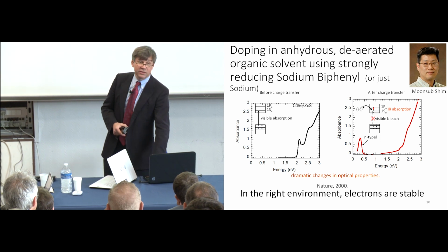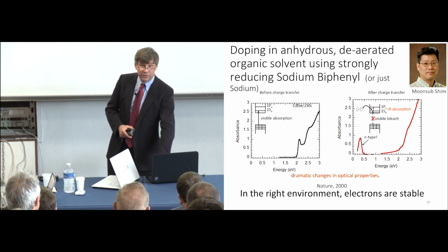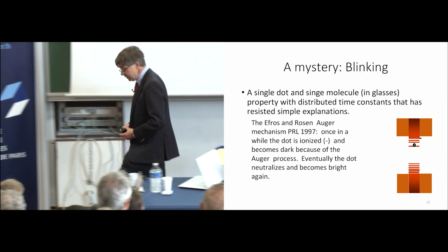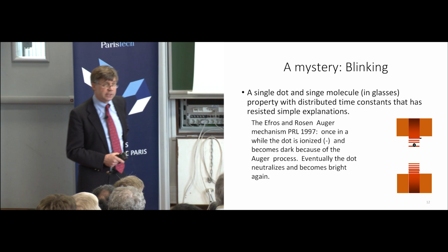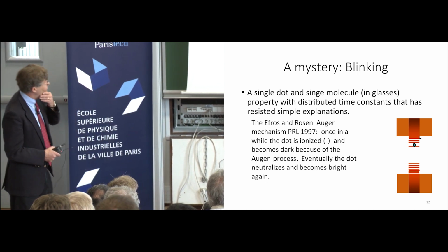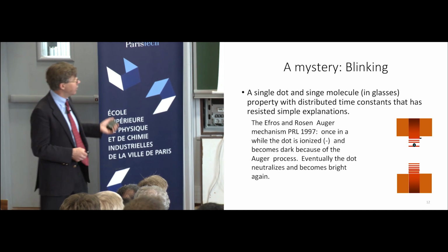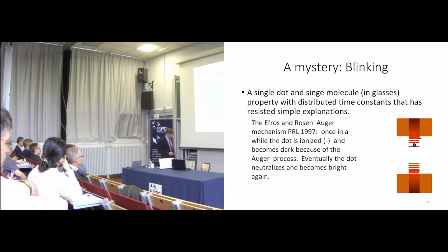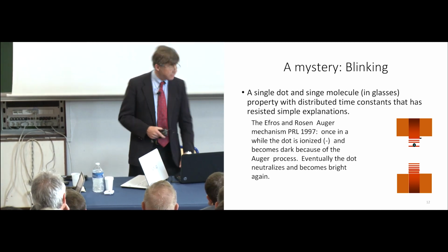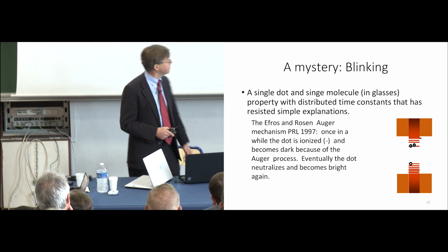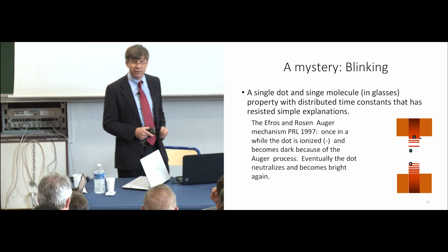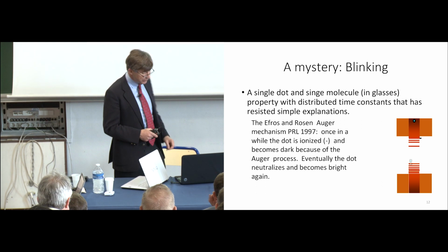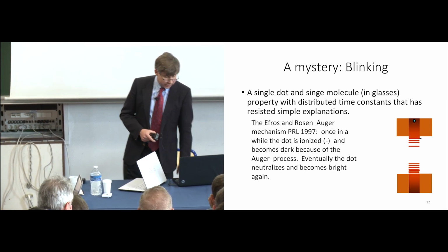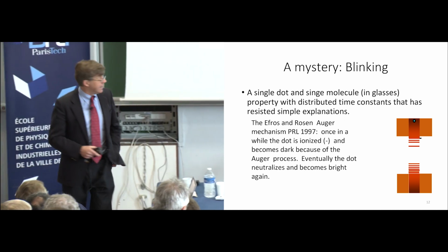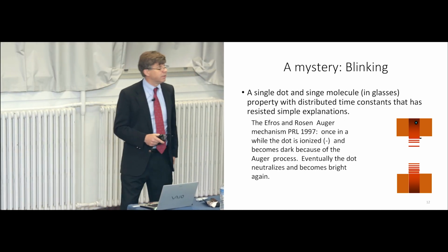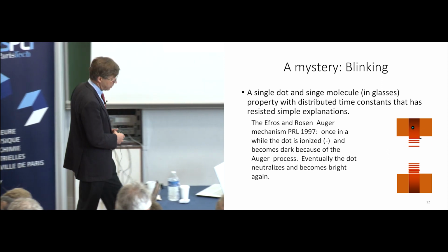But that was exciting, and I think it's going to be something for the future, of course, to charge the dots and try to make them lase better. So there was a mystery, blinking, which was intimately connected with the charge, and that was because of Sasha. Sasha proposed that a dot once in a while gets ionized, and if it's ionized, then there would be an Auger process, like if you create an exciton, there would be a very fast non-radiative process where the electron recombines with the hole, kicking the other electron far out, and then that electron would just recombine non-radiatively to the bottom of the band. And so basically, the electron catalyzed non-radiative recombination. And so that was Sasha's and Efros and Rosen mechanism.